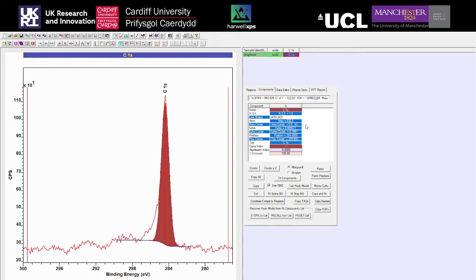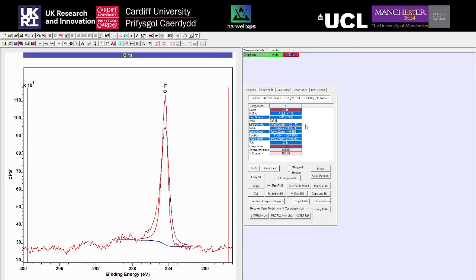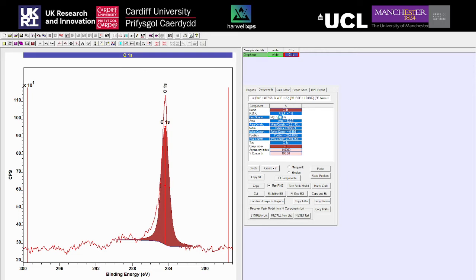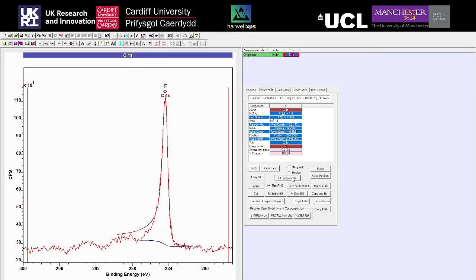We've got these modifiers a and b. What we're going to do is add another one separated by commas, so we've now got a, b, and z, which we can use to independently modify each side of the peak. Rather than just having two numbers separated by a comma, we've now got three numbers separated by a comma, still within LA brackets. We'll start off at one and look to modify either side. Going to a fairly extreme example — going to 0.5 — you can see straight away we've got more of a tail spread on the high binding energy side than on the low binding energy side.